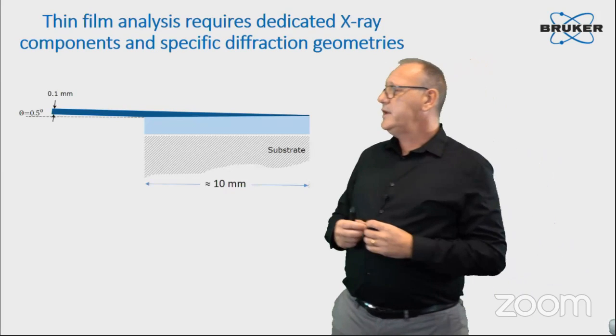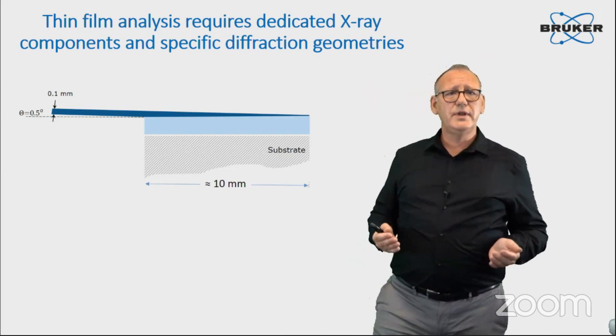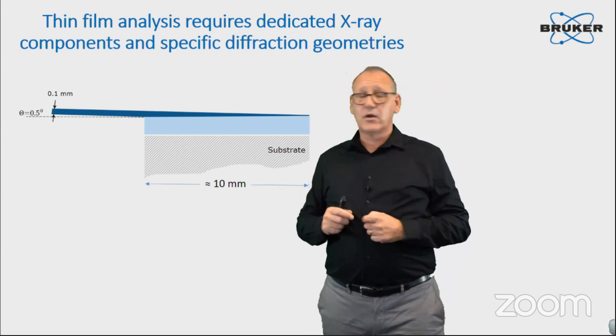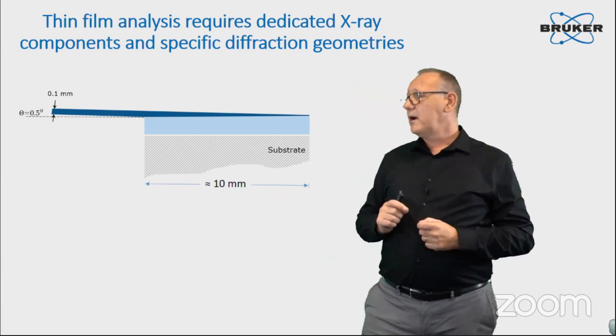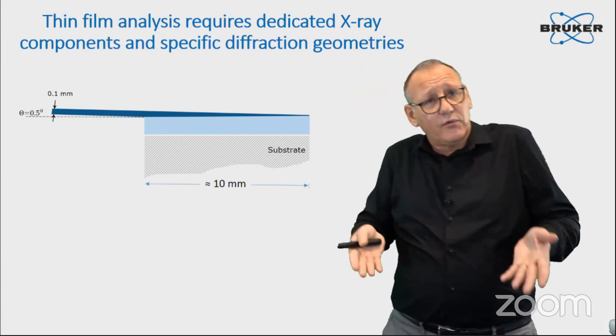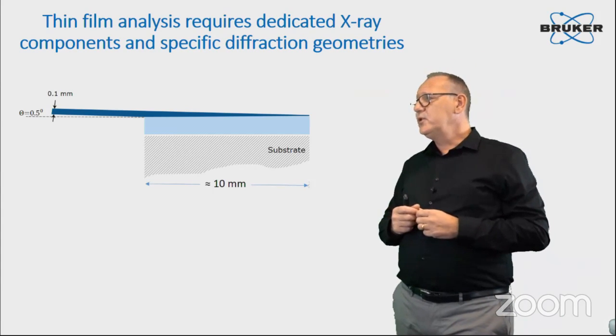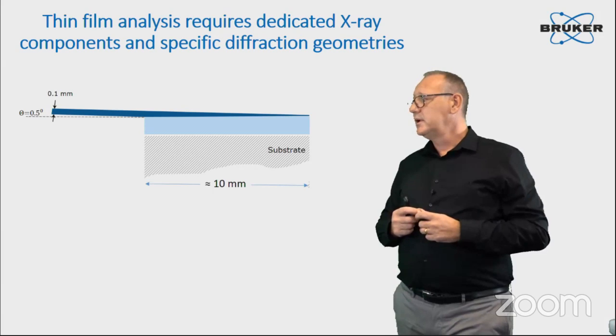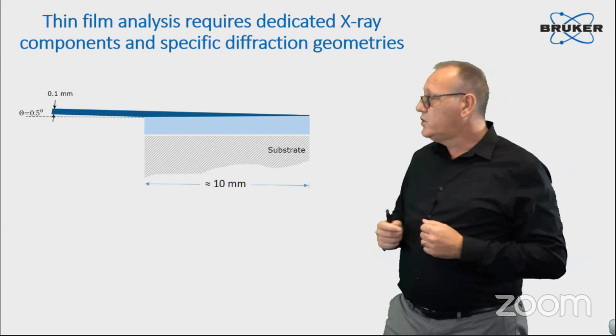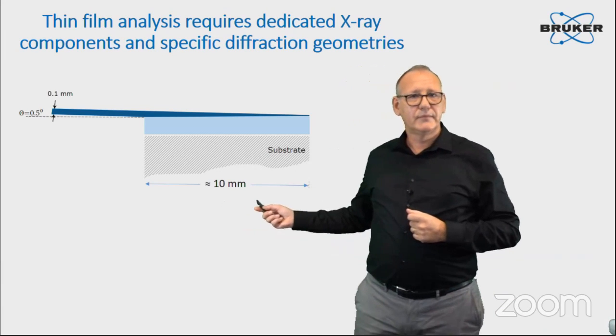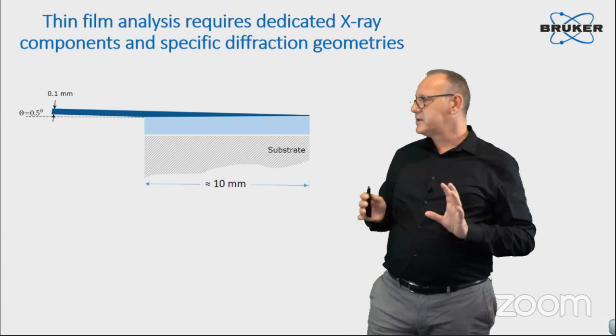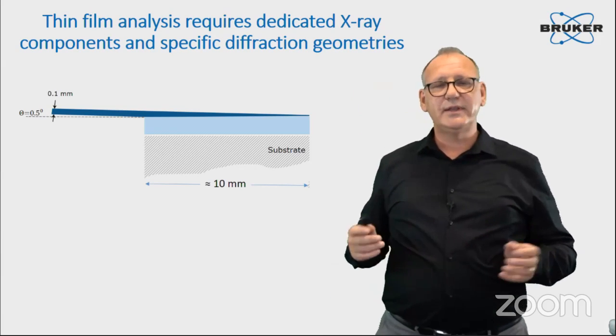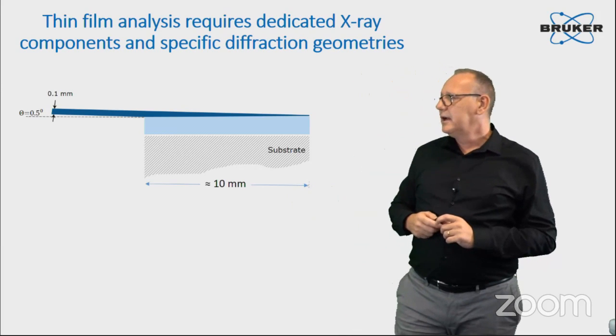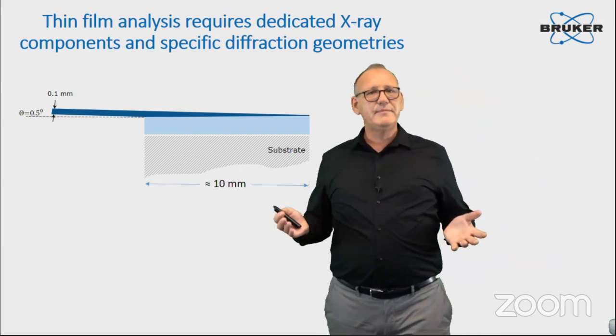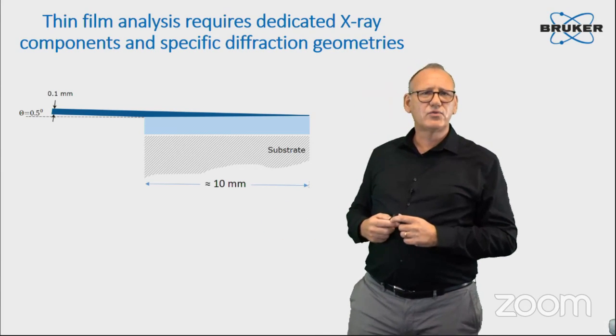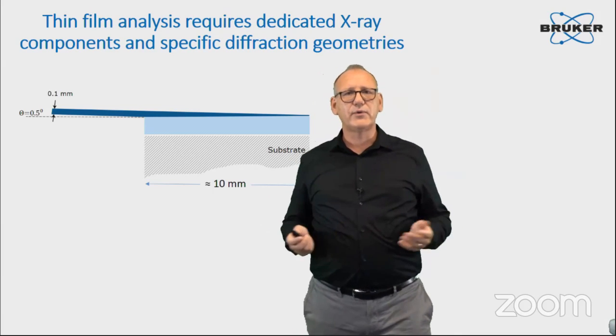In grazing incidence diffraction, you need to use an extremely low incident angle. Here we have an incident angle of 1/2 degree, which is typically what we will need to use for those very thin layers because we want to avoid the signal from below. If you use a 100 micron exit beam out of your source, due to the footprint effect at low angle, you will have a footprint size of 10 millimeter already. And 10 millimeter is probably the size of a typical research sample, maybe 10 millimeter, maybe 20 millimeter. But that means that whatever beam size you have out of your source, you will have to strongly reduce the size to something in the range of 100 micron.